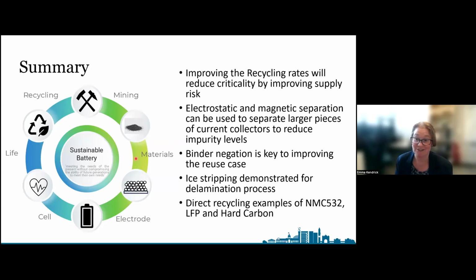We've also shown that ice stripping can be used for delamination. It has a lot less waste associated with it, and because it's so quick, less energy as well for delamination. And we can use both of these processes to show that we can start to direct recycle things like NMC 532, LFP and hard carbon, which have been shown here as examples.